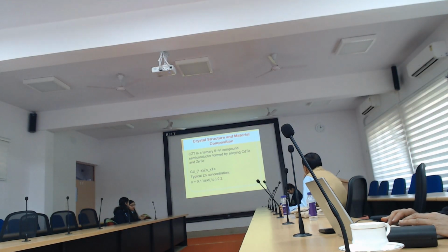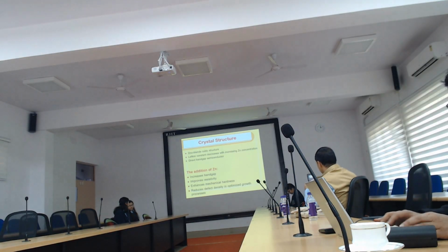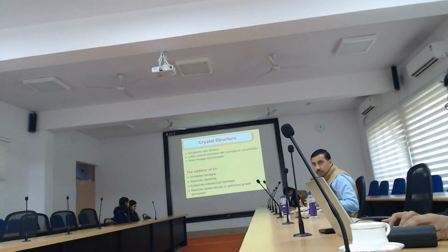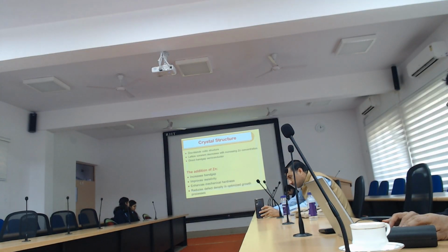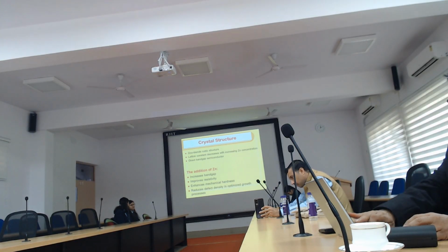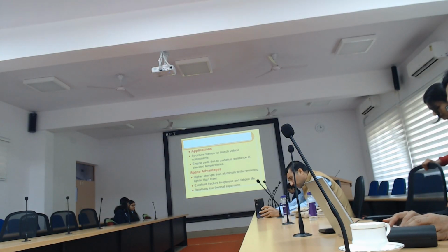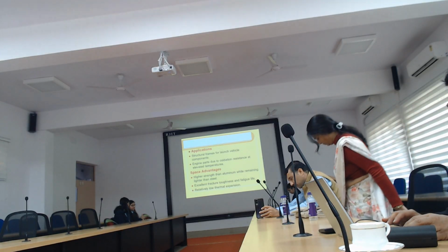The structure and material composition. Then we have the zinc blende cubic structure, whose lattice constant decreases with increasing zinc concentration, a direct band gap semiconductor, and in addition to that, it increases the band gap, improves the resistivity, enhances the mechanical hardness, and reduces the defect density in optimized growth processes. It has wide application in the field of space physics, structural frames for launch vehicles components,